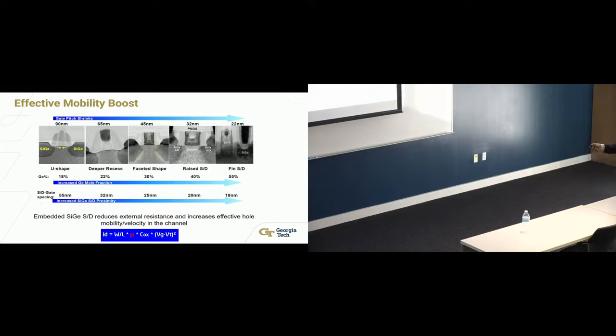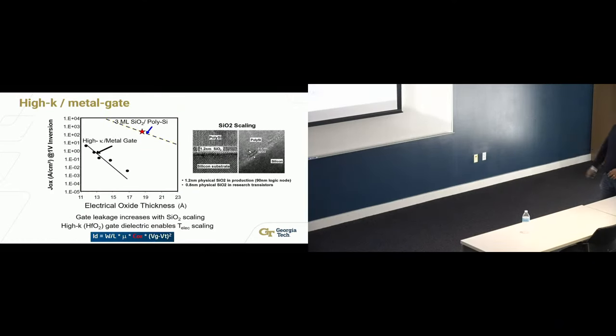Now, of course, we have gone back to not doing planar, but we'll talk about this 3D geometry. What you see here is that in state-of-the-art transistors, the ones you're using in your latest, greatest devices, germanium could be as high as 55%. So it's almost more germanium percentage than silicon percentage.